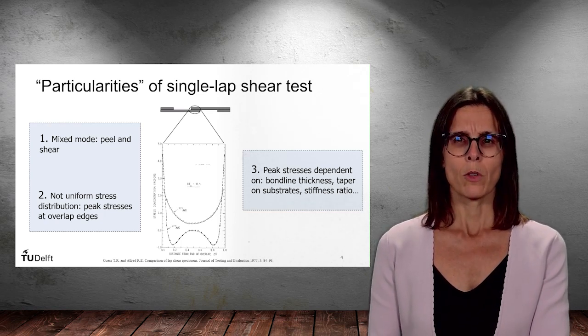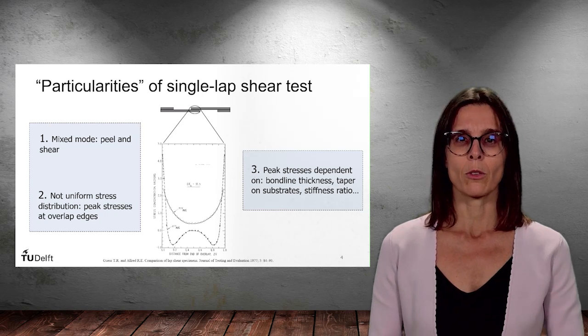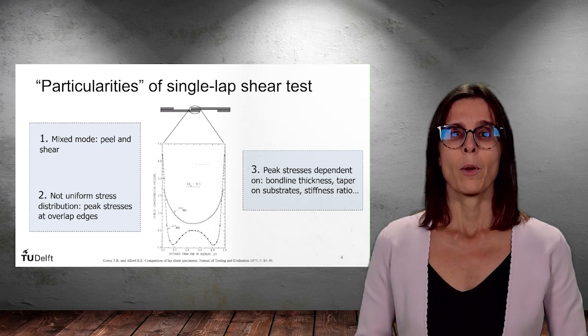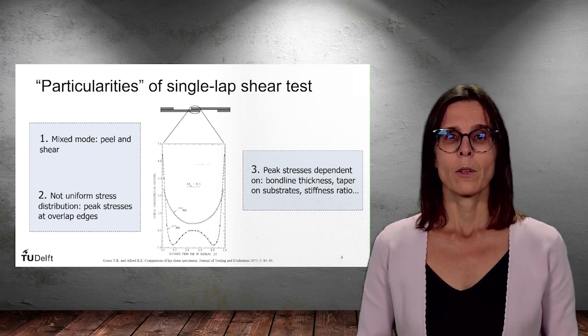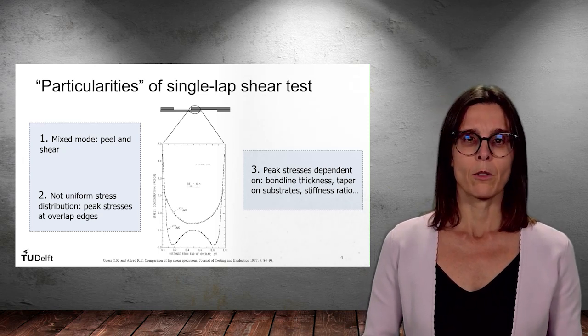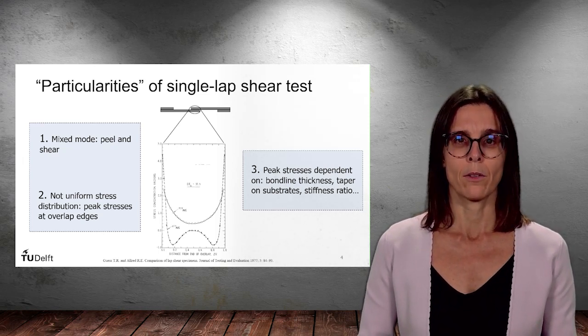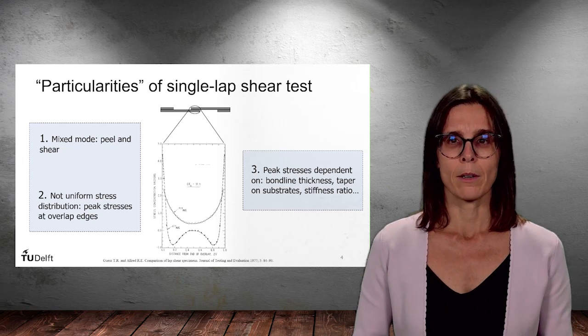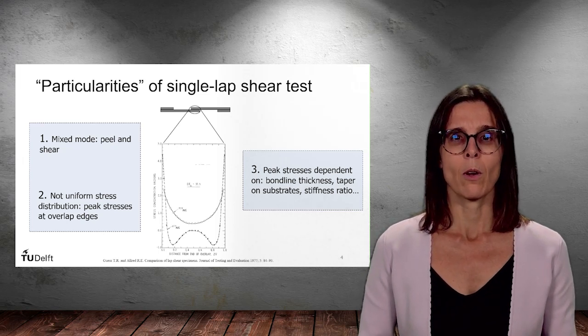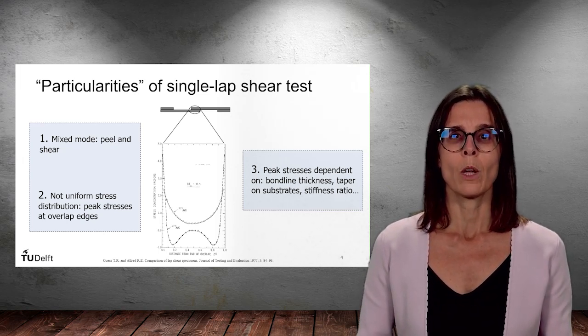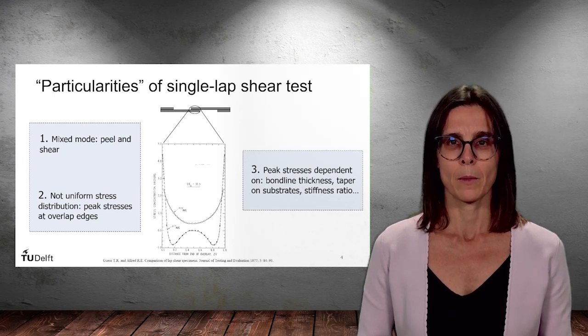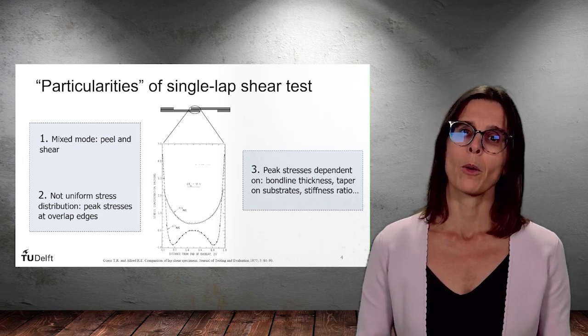Finally, these peak stresses are sensitive to numerous factors such as bond line thickness, whether the adherends are tapered or not, the presence of fillets, or the stiffness ratio between bond line and adherends. Despite these particularities, the single lap shear test is commonly regarded as a useful tool for comparison and process development. Let's see how that works for composite welded joints.